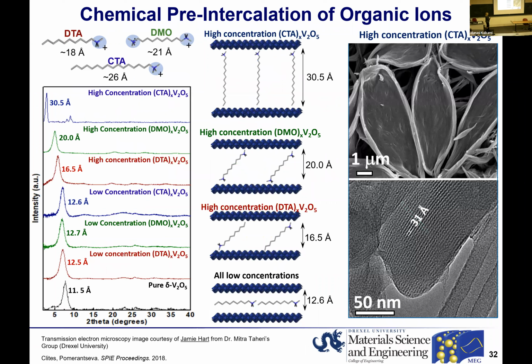And what we found is that when we used a low concentration of these three different organic molecules with different lengths shown here, we synthesized products with the same interlayer distance. So we believe that when the concentration of organic molecules is small, they reside parallel to the vanadium oxide layers, occupying this interlayer region. And as we increase the concentration of organic molecules, they might reorient themselves and expand the interlayer region. So now at high concentration of organic molecules, we see the correlation between the length and interlayer distance in the final product.